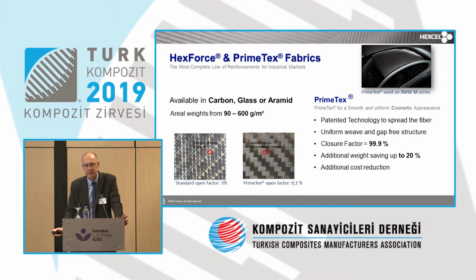In that particular case, we have closed weave and uniform cosmetic appearance. The filaments of each tow are spread out, so that it can actually reach a closure factor of close to 100%. An interesting thing about that technology is that it enables us to go lower in weight, down to, for example, 98 grams for a 3K, where normally you would be using 1K material. So that's really something that enables good cosmetic appearance, but also cost saving and weight reduction.